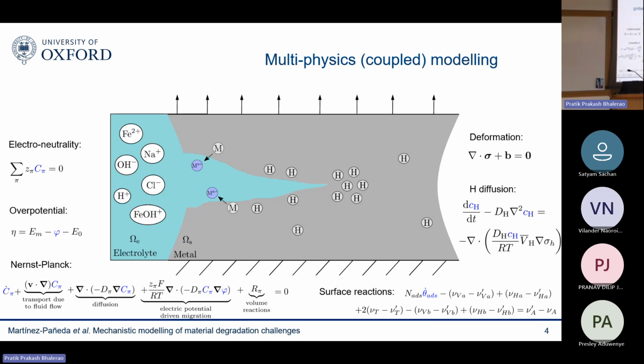So if I look at Nernst-Planck, you have transport due to fluid flow, diffusion, electromigration. And as you can see, all of them rely on parameters that have a clear physical meaning and that we can independently measure in our labs. So you have diffusivity, temperature, Faraday's constant, and so on. So there are no alpha, beta parameters that you magically fit to an experiment. These are all parameters that you know before you run your calculations.